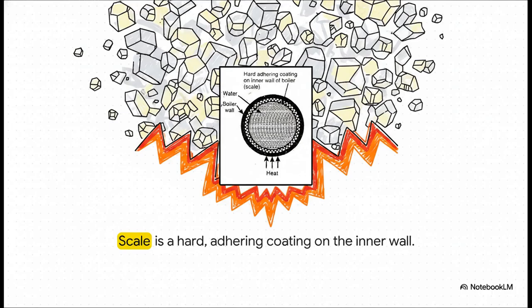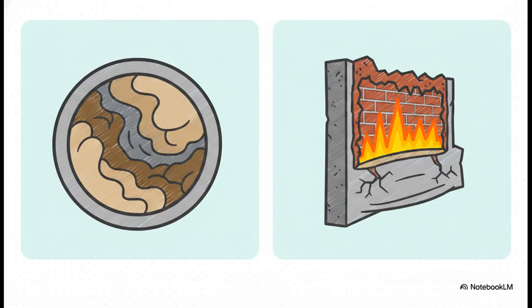While sludge is soft and loose, scale is this terribly stubborn, hard, super adherent coating that literally bakes firmly onto the inner walls. It's formed by substances like calcium sulfate and silica, which actually become less soluble as the temperature skyrockets. So instead of drifting around, they precipitate directly onto the absolute hottest surfaces of the boiler plate. To put it simply, sludge chokes the flow, but scale suffocates the metal. Sludge can definitely clog up your pipes and lower your boiler's efficiency, for sure. But scale is far more dangerous.